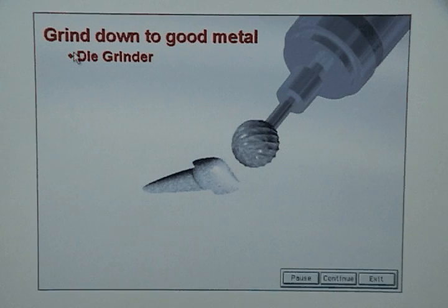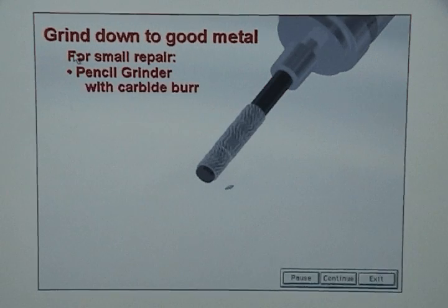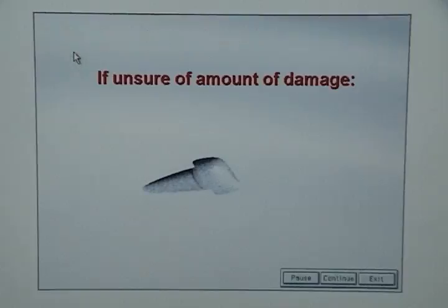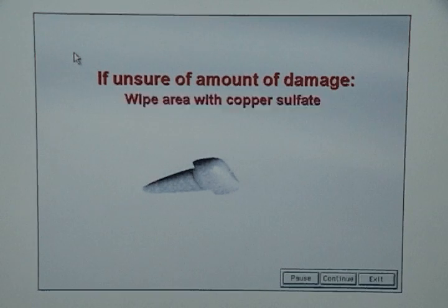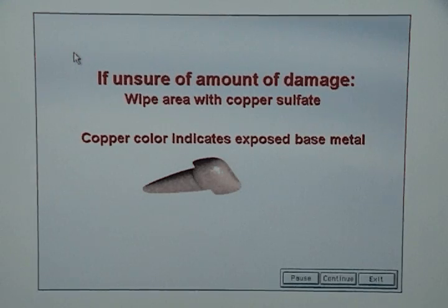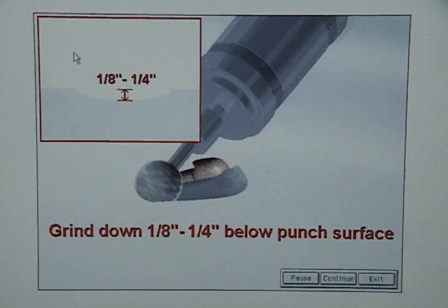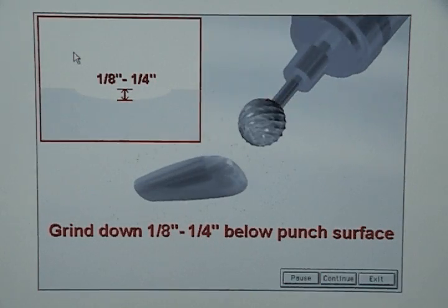Then, grind the defect down to good metal using a die grinder, or, for a small repair, a pencil grinder with a carbide burr. If the punch is chromed and you are not sure about how much chrome is damaged, you can wipe the area with copper sulfate. A copper color will appear wherever base metal is exposed. Grind the damaged area down to between 1/8 of an inch to 1/4 of an inch below the punch surface.